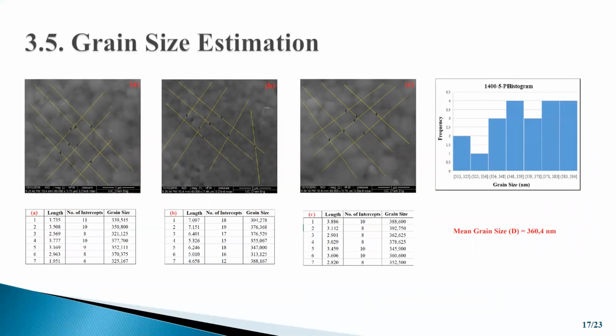The mean grain sizes of the sintered pellets were estimated from the SEM micrographs using the linear intercept method from 3 different micrographs. The process of estimating the mean grain size of the sample sintered at 1400 degrees for 5 minutes is given in this figure. A random straight line is drawn through the micrograph. The number of grain boundaries intersecting the line are counted, as we can see in this table. And the average grain size is found by dividing the line length by the number of intersections. We repeated this process 3 times to reduce the standard error.